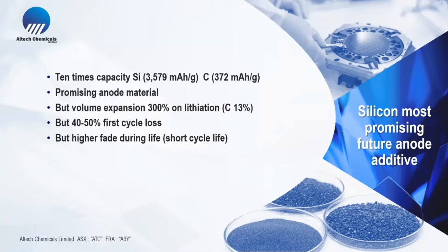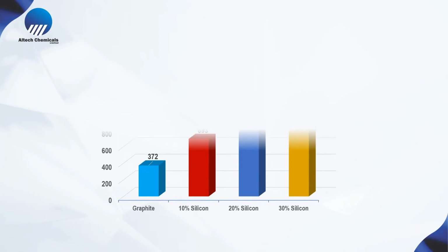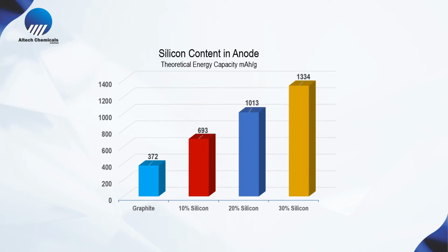First, there is a volume expansion of the silicon particles where it fractures. Number two, instead of the first cycle loss of 10%, it's close to 50%. So 50% of lithium is lost. And also it has a higher fade in the battery. So these are the three problems, but the potential for silicon is enormous. This is a graph that shows graphite material at 372 milliamps per gram. If you add 10% silicon, it jumps to 693. With 20% silicon, it goes to 1,000.